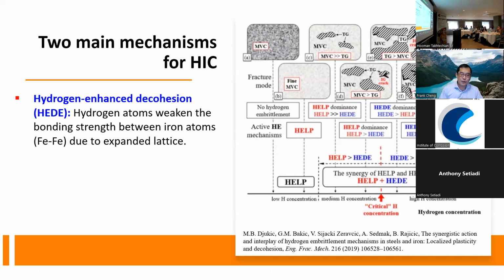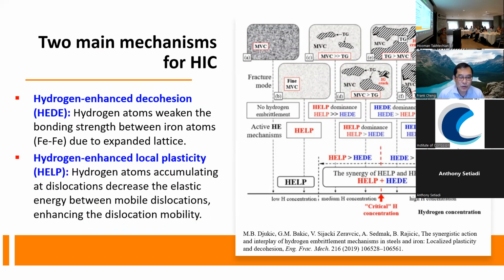So why can hydrogen reaching a certain concentration make the crack initiate? Of course, if you have a chance to review the literature, you can find lots of different mechanisms. But there are two main mechanisms that are very popular for hydrogen embrittlement. The first one is HEDE, the hydrogen enhanced decohesion mechanism. Based on this mechanism, hydrogen atoms can weaken and break the bonding between Fe and Fe. The second one is the hydrogen enhanced local plasticity mechanism. According to this mechanism, hydrogen atoms can combine with internal dislocations and decrease the energy required for dislocation movement. In this way, the hydrogen can increase the mobility of dislocations.